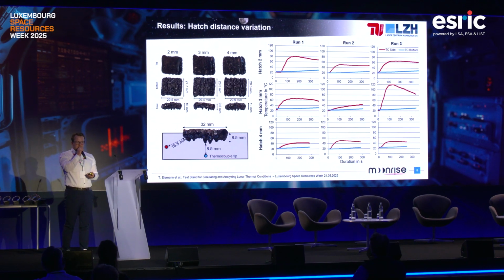Here you can see our samples. They do not show significant differences in terms of dimensions or mass. And we saw that with a smaller hatch distance, we tested 2, 3, and 4 millimeters, by the way, with a small hatch distance, the surface gets smoother.